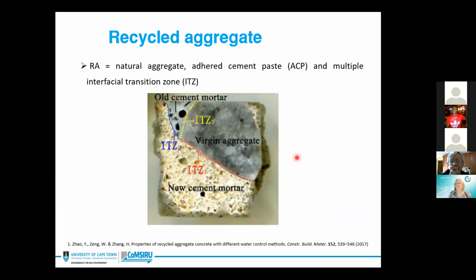So here's a picture of recycled aggregates. Now, recycled aggregates can be idealized as constituting virgin aggregate and old adhered cement mortar. The old adhered cement mortar comes from the old concrete that was crushed to produce the recycled aggregates. Between the old adhered mortar and the virgin aggregate, there is an interfacial transition zone. We can also see that the old adhered mortar looks porous and is less stiff than the aggregate component. For this reason, recycled aggregates usually have high water absorption, and they are less stiff and less dense than conventional or natural aggregates.